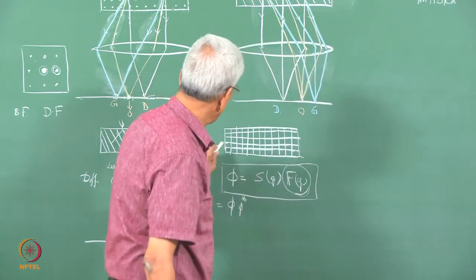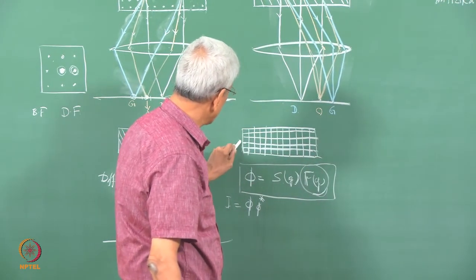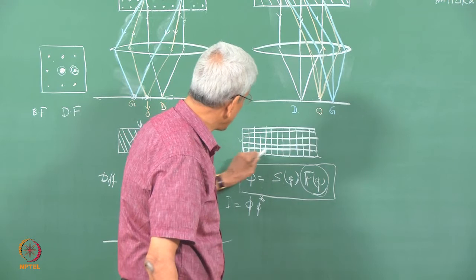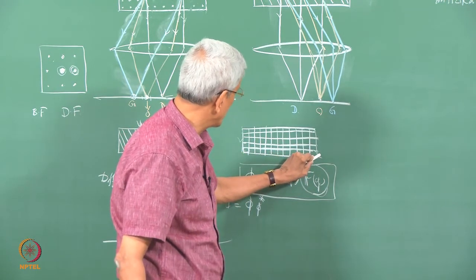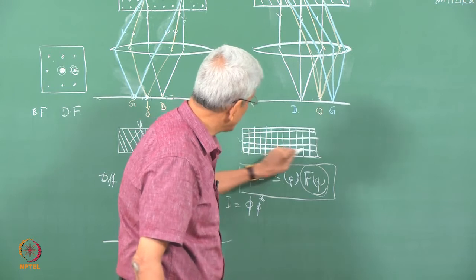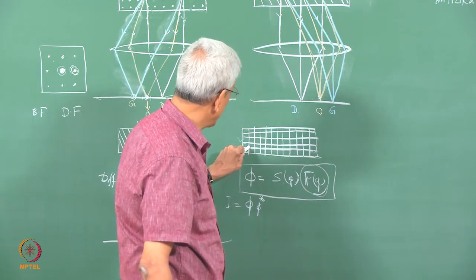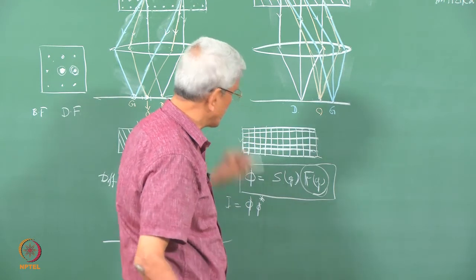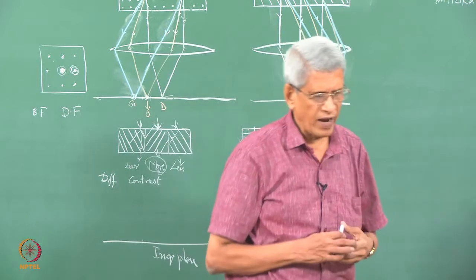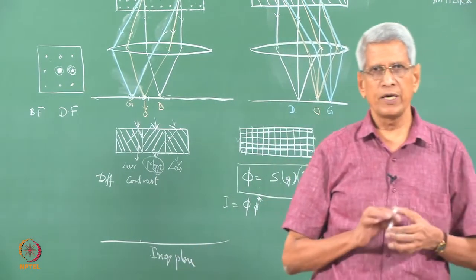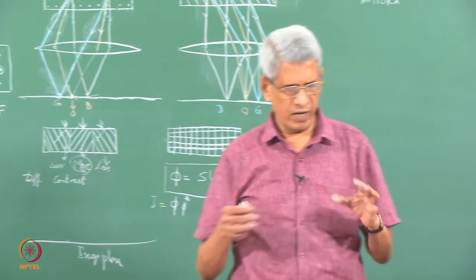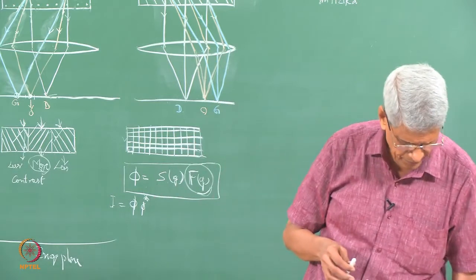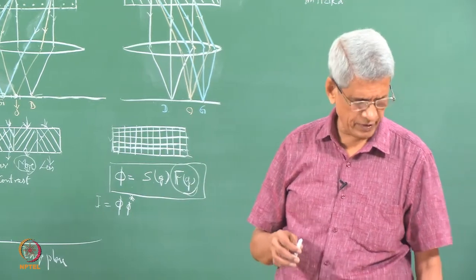As you can make out, the number of unit cells in this direction is about 5 or 6. The number of unit cells in this direction is going to be more, depending upon the number of unit cells in that particular direction. The sharpness of the diffraction spot in those directions will change. That is why this factor is called the shape factor. Looking at the shape of the diffraction spot, we can find out the shape or the morphology of the sample.